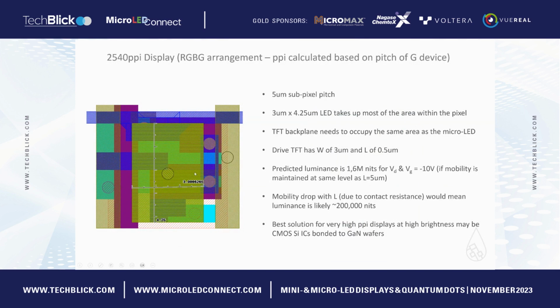Finally, this is just an example of a very high resolution one. This is more of a conceptual one because we don't have the capability to pattern down to the 0.5 micron channel lengths required for this. And this predicts a luminance of about 1.6 million nits, but that's based upon a charge mobility of about 2 centimeters squared per volt second. It's likely that with the shorter channel lengths we will lose a lot of performance in the drive transistor. So therefore, the brightness is likely to be much lower, something like 200,000 nits.